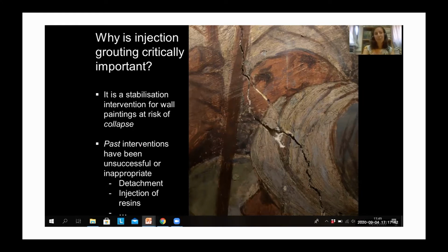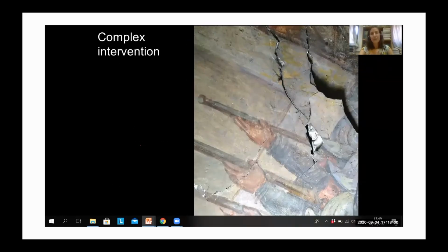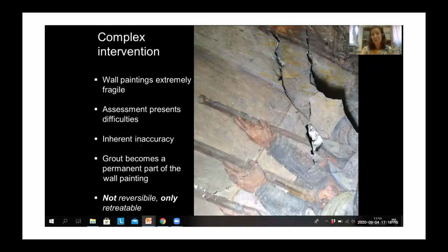So, not very recently, but in the last decades, I think that conservators mainly agree that injection grouting, if possible, is actually a more appropriate intervention in case of delaminated wall painting. It is actually rather complex very often, as conservators of wall paintings, I'm sure, know. Why? Because as we can see from these pictures, often wall paintings that need injection grouting are in an extremely fragile condition. We can see, for example, this very bulky delamination here, and it is clear that this is really unstable and fragile.